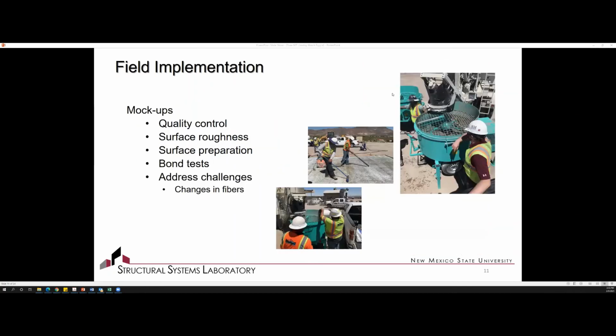Okay. So as we began this field implementation, as part of the requirements for the contractor, we had to do a mock-up. We were there to look at quality control, surface roughness and surface preparations. We did some bond tests with this, really just to address any challenges that we had. And one of the biggest challenges actually came really early on, when we had to change the fibers. As many of you might be aware, the fibers that were produced in the United States changed, and so we had to go to a different fiber and make some modifications there. And I'll address that a little bit on a few later slides.